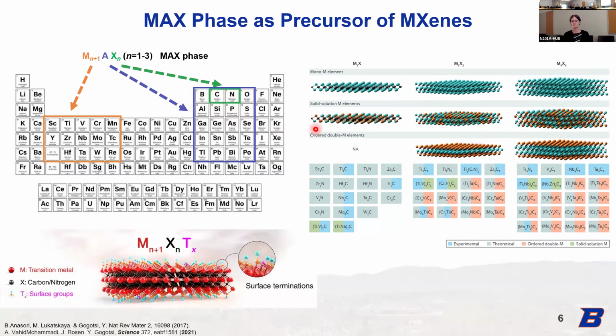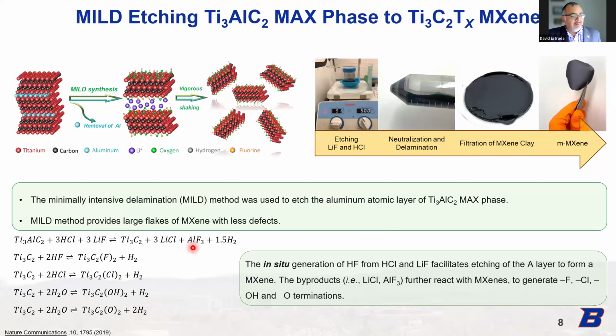It shows here too, after you etch away the A element in these MAX phase ceramics, you get the MXene phase, right? You get the transition metal and the X, the carbon or nitrogen, and then in that etch process, we also develop a surface functional group, which tends to be hydroxyl, oxygen, chlorine, of the transition. In our group, we went to Drexel.